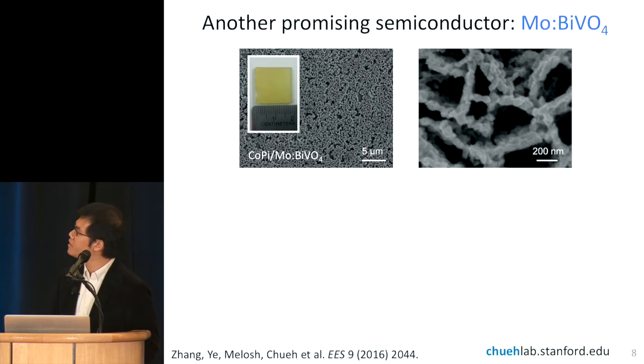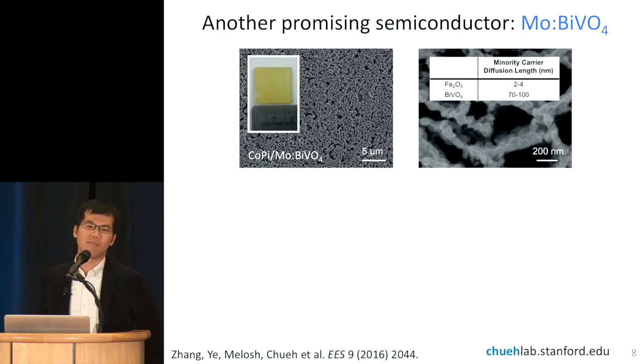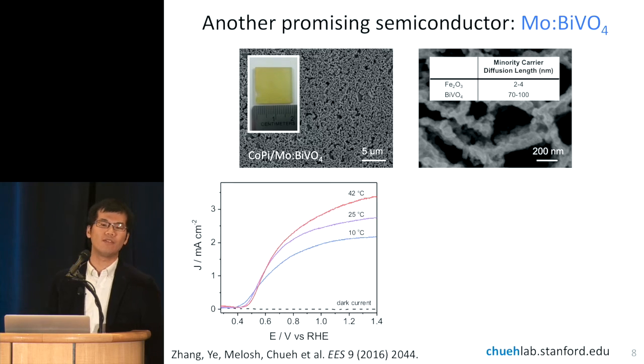So we switched to a different material. This is bismuth vanadate doped with molybdenum. And this is the type of nanostructure that we have been able to create by a combination of electrodeposition and annealing. Let me just point out, the minority carrier diffusion length here is much larger than in iron oxide: 2 to 4 nanometers for iron oxide and about 70 to 100 nanometers in bismuth vanadate. The space charge region is comparably thick in both, on the order of a few to 10 nanometers. This results from the high doping level that we have to use in order to get enough majority carrier mobility. And the results were even more encouraging.